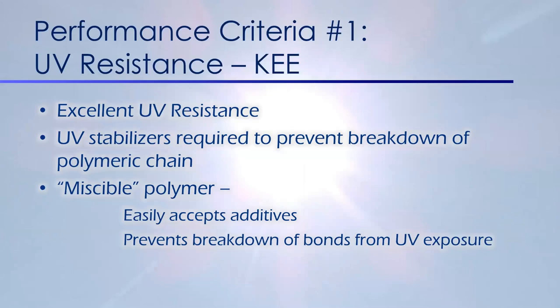And KEE, or the Elvaloy in KEE, was actually originally designed as a solution to mitigate the plasticizer migration issue on the roof. So in your KEE membranes, the Elvaloy is an excellent UV resistance. The UV stabilizers prevent that breakdown of that polymeric chain with that liquid plasticizer, because the Elvaloy in your KEE sheet is a dry blend that kind of wraps itself around that PVC molecule, providing a permanence of that Elvaloy and the UV resistance during the life of the product. So again, like PVC, KEE is a miscible polymer. It accepts additives very easily and prevents that bond through that Elvaloy molecule to prevent that UV exposure.